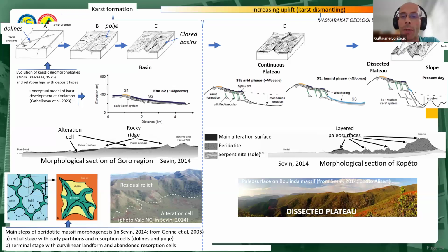This figure shows the relationships between the development and evolution of karst systems at the top and the geomorphological types of nickel laterite. The onset of weathering is controlled by faults and dolines develop at fault intersections. Closed basins then developed around these intersections and along the structures. The basin type corresponds to the alteration cells surrounded by rocky ridges, as I've already seen in previous slides. This basin type is illustrated by this morphological section at Goro.